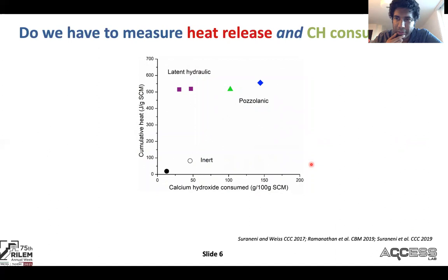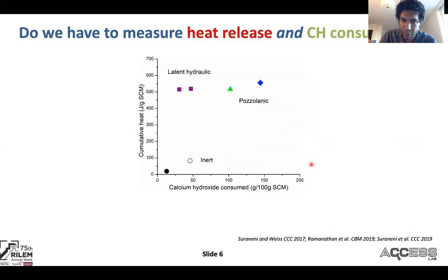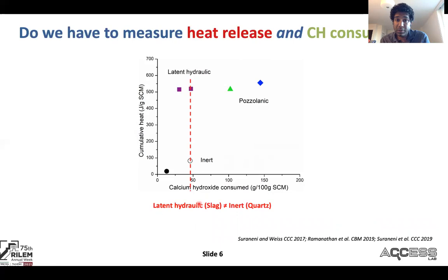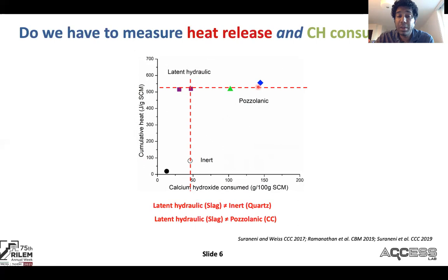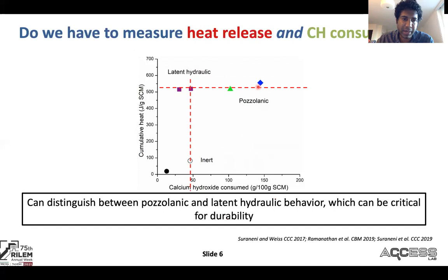One of the main things this test does differently from other tests is that it measures both heat release and calcium hydroxide consumption. Do we need to measure both? The answer is yes — if you consider the calcium hydroxide consumption of slag and quartz, they could be similar even though these are very different materials. Similarly, heat release of slag and calcined clay could be similar. But if you measure both, there is absolutely no confusion: you get a very clear image of the material reactivity and have separated out the pozzolanic and latent hydraulic behavior, which is really important for durability.